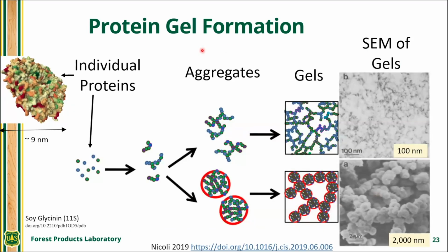So, how do protein gels form in food? Because the food industry has done a lot of work on how these things happen. This is a huge area of interest for the food industry. So, individual proteins, you expose them to heat, typically in water. Denaturation often results in a more hydrophobic surface. So you raise the temperature, these proteins rearrange into balls with more hydrophobic residues on the surface. They stick to each other, sometimes through disulfide, but often through hydrophobic interactions. And they continue to aggregate. Sometimes they aggregate into big balls, and sometimes they aggregate into strings. And then they get big enough that they percolate, and now you have a gel, and this is what they look like in the SEM.